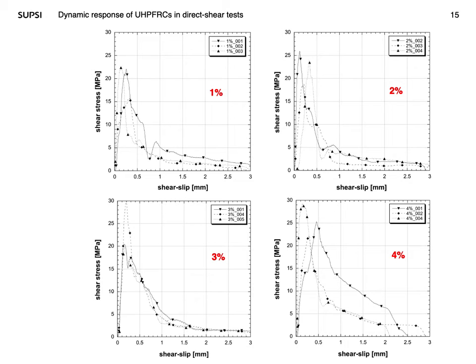we can observe the shear stress versus shear slip curves of the four ultra-high performance fiber-reinforced concrete. Increasing the percentage of fibers an enhanced shear capacity is obtained. The deformation capacity is also incremented, allowing higher distortion to the material. This effect could permit to the structure made with these materials a higher deformation, as a result, higher ductility.